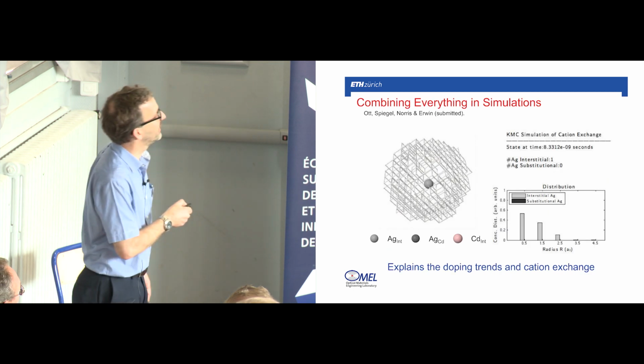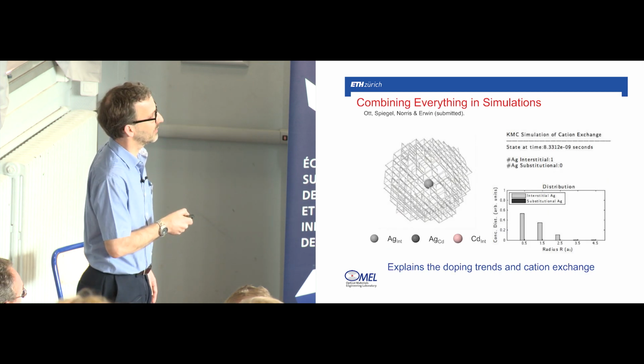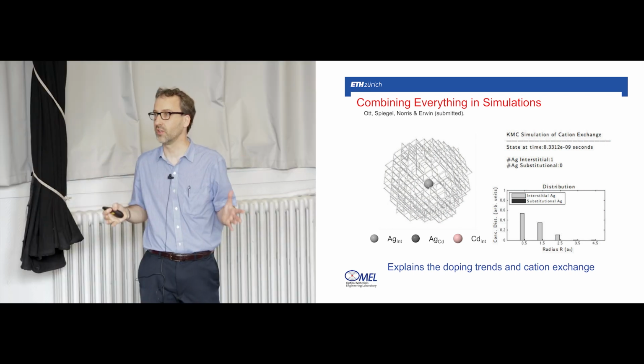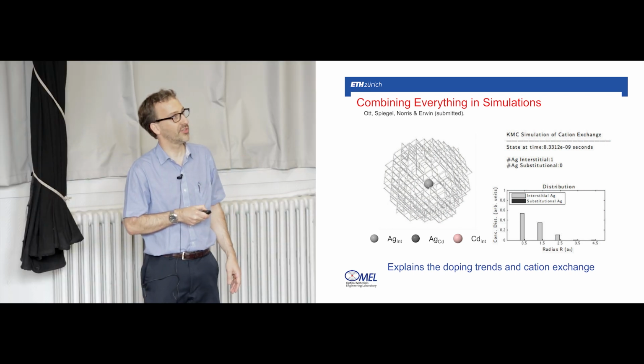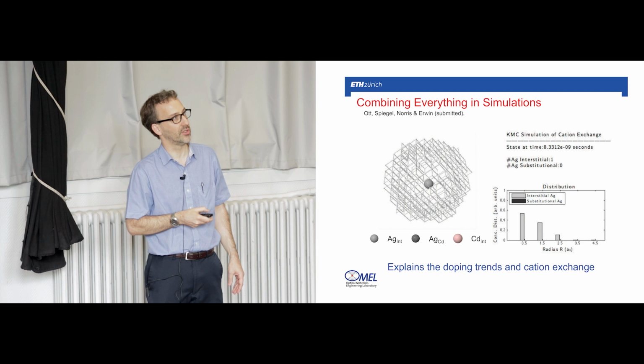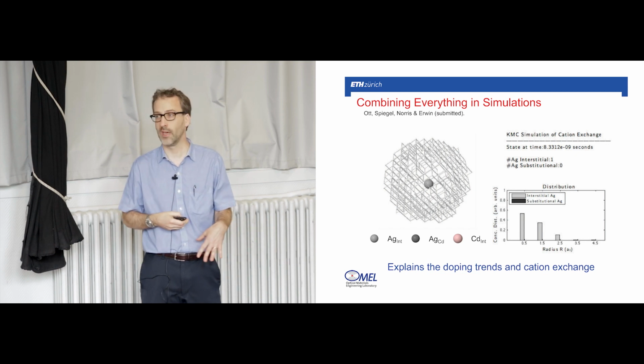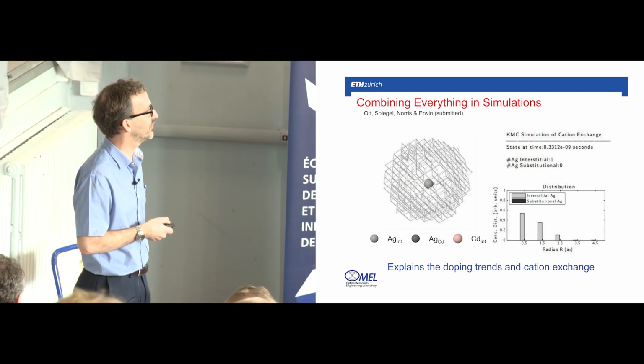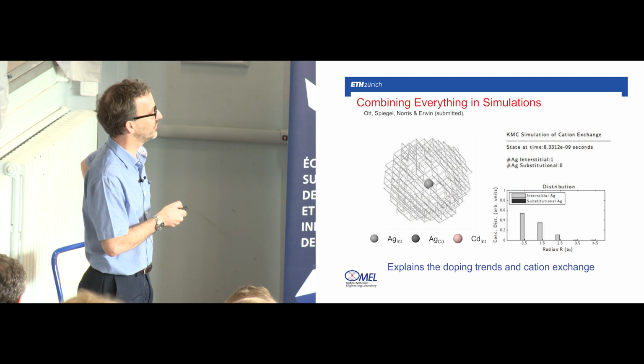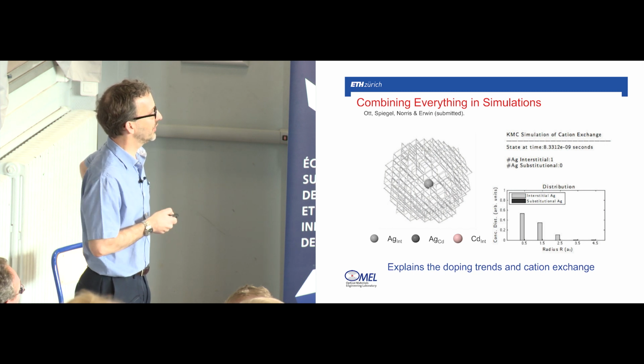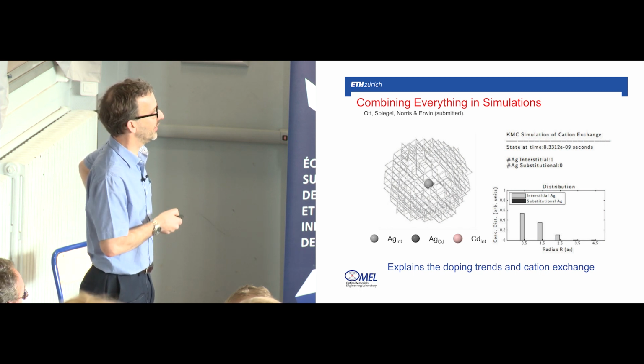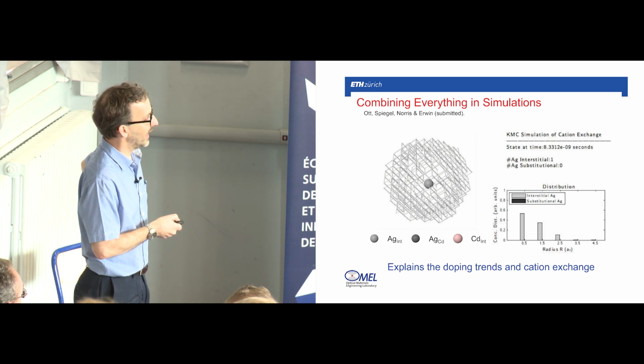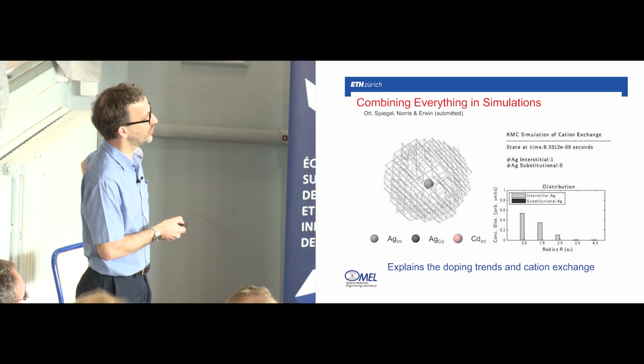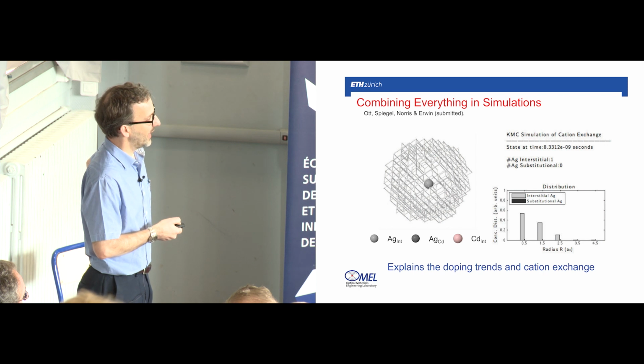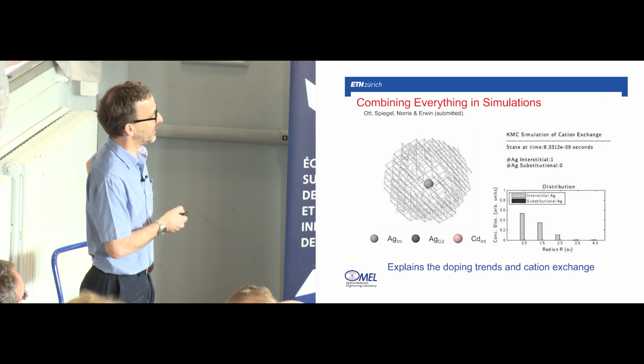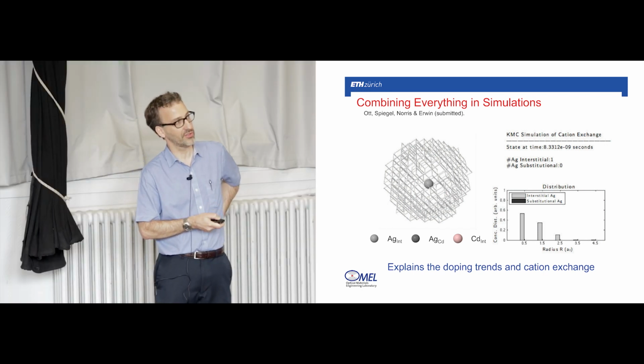Florian and Steve did these kinetic Monte Carlo simulations to put all of these calculations together. So this is an interstitial silver inside a nanocrystal, and you can figure out at each step of the simulation what the possible reactions are and what can happen. Here it is diffusing around inside the nanocrystal, and it's being repelled by the barrier because it's positively charged. And if you look here, this is the radial distribution of this silver. As we add more, they have to repel, they have to keep away from each other and the surface.